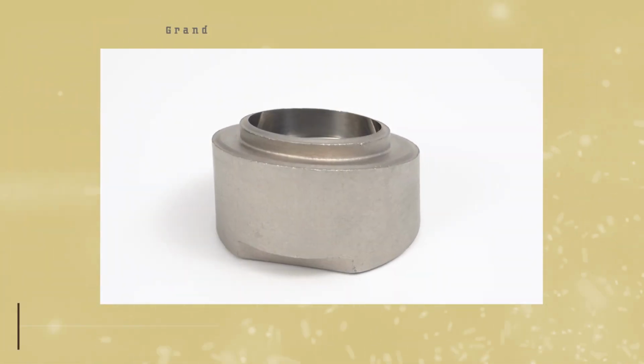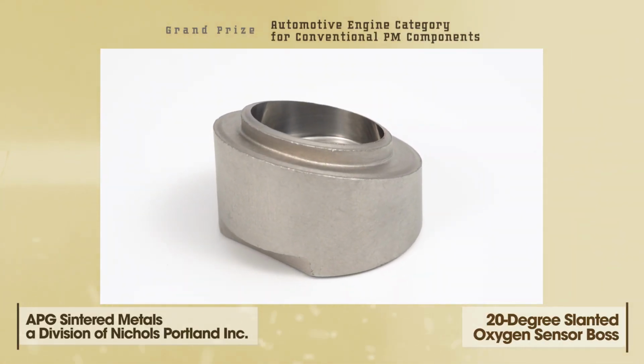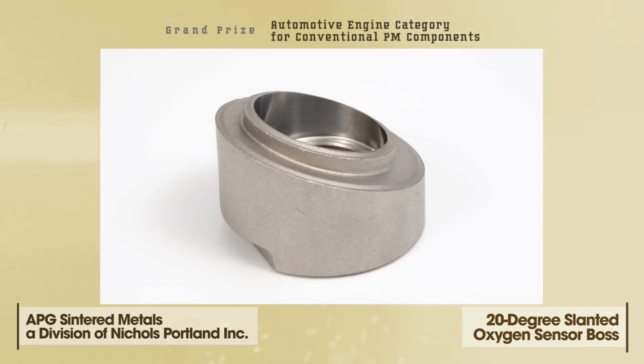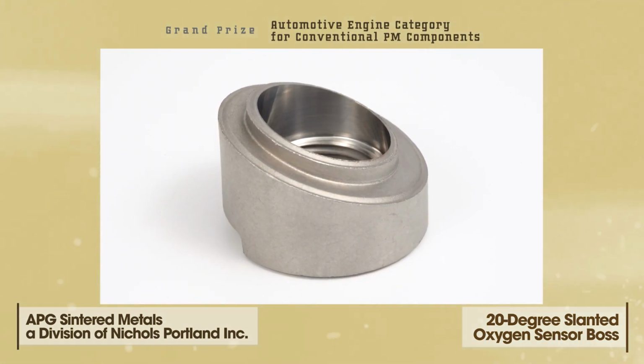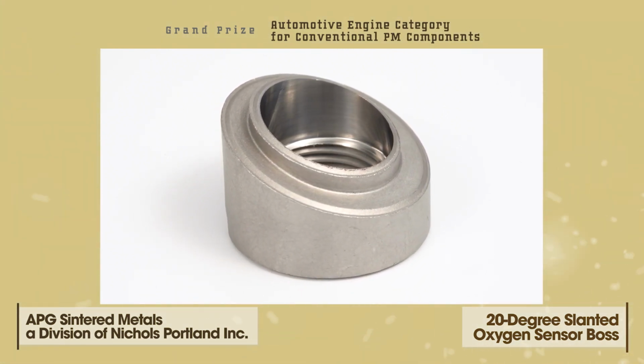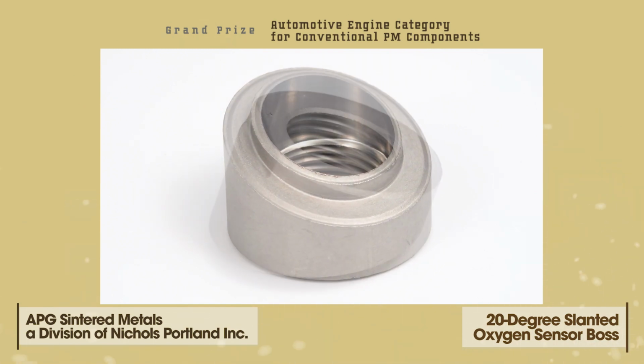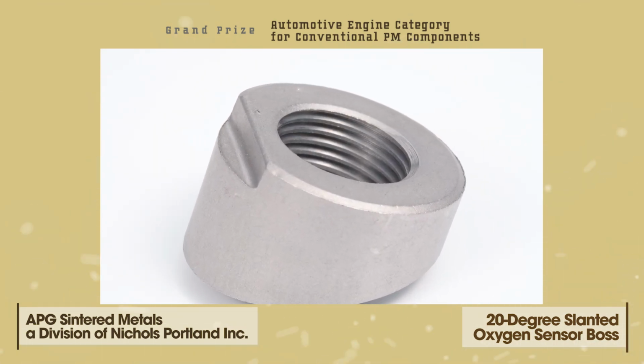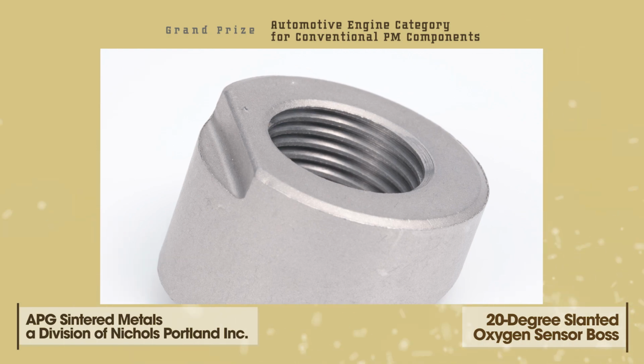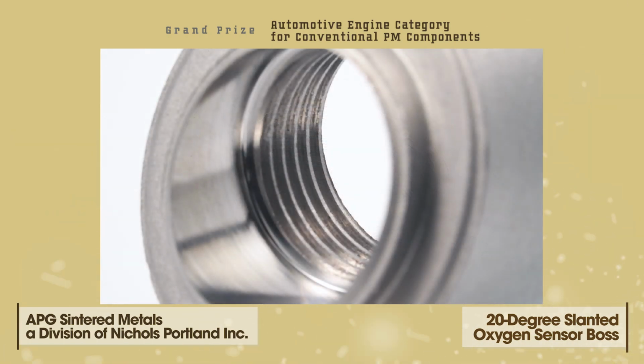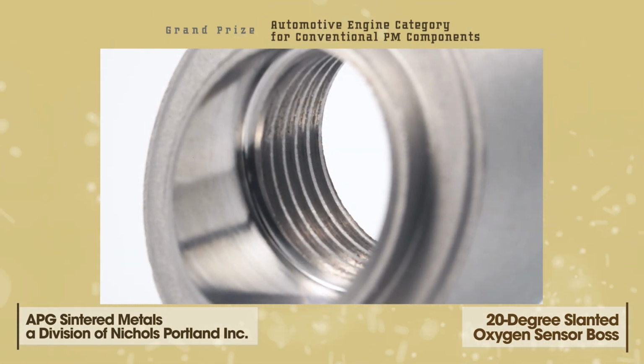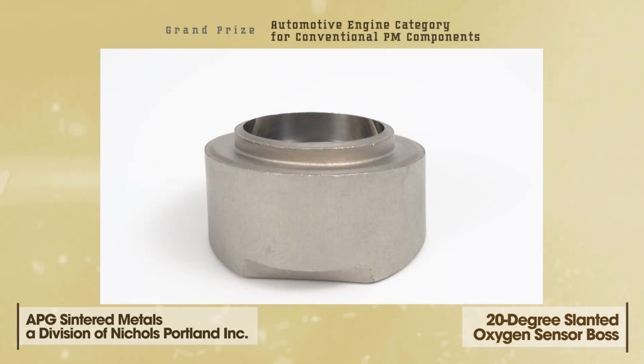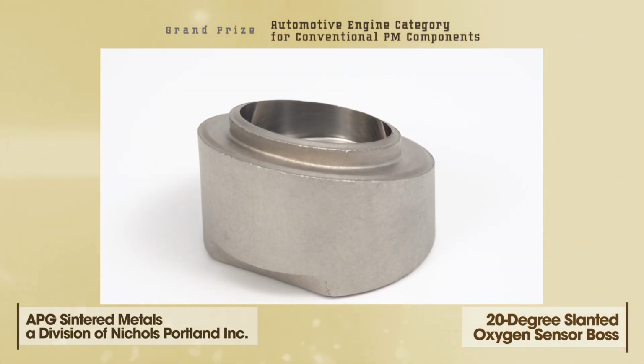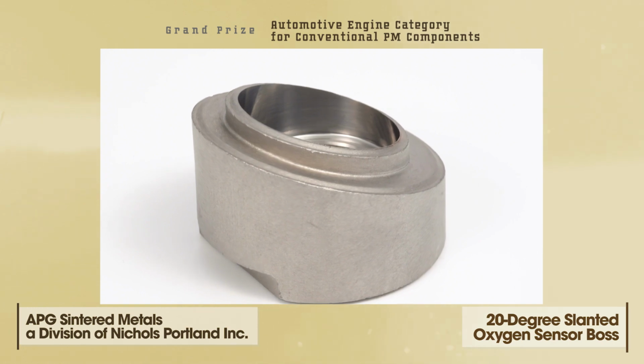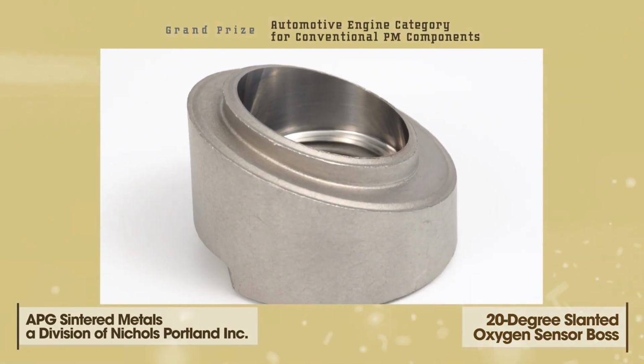APG Sintered Metals, a division of Nichols Portland Incorporated, received a grand prize in the automotive engine category for conventional PM components for a 20-degree slanted oxygen sensor boss. This 20-degree slanted oxygen sensor boss is used on a V6 pickup truck catalytic converter. The stainless steel sensor boss is produced by compacting to near net shape, delubricating in a low-temperature belt furnace, and sintering at 1315 degrees Celsius in a high-temperature pusher furnace in a hydrogen atmosphere.